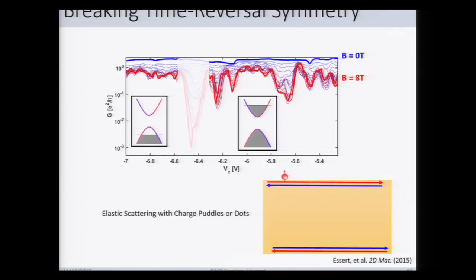And what we can understand, one thing that we can draw from is some theory work in the literature, which has shown that if you have small puddles due to disorder in your device and a finite magnetic field, then you enable elastic backscattering. What you can understand is that when, say, the spin-up forward-moving electron hops into the puddle, it can then randomize its spin, and then it will have a 50% probability of jumping in a forward direction or a backward direction, and therefore backscattering has been enabled.